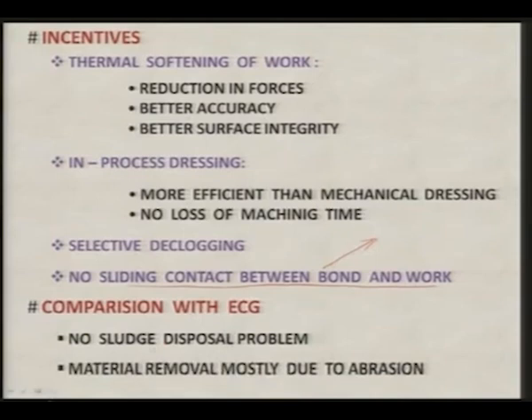Now, material removal mostly due to abrasion is taking place in general grinding, but in electrochemical grinding this is not really true that most of the material removal is taking place due to the abrasive action. In case of electrochemical grinding, about 10% of material removal takes place due to the abrasive action, while 90% takes place due to the electrochemical dissolution.